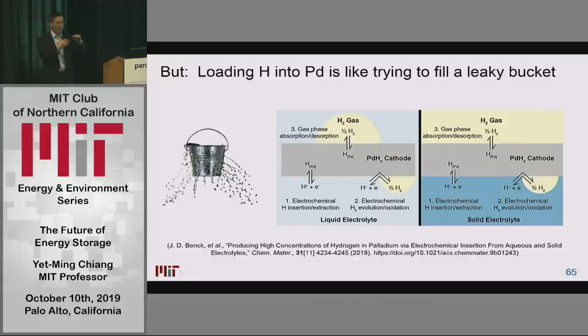The beauty of electrochemistry is that with a turn of a knob and fractions of a volt, you can apply a chemical potential, a thermodynamic driving force, that's equivalent to many, many gigapascals of applied pressure. That's why we use electrochemistry. Otherwise we would have to build a giant pressure apparatus to do the same thing that we can do with 100 millivolts or so.